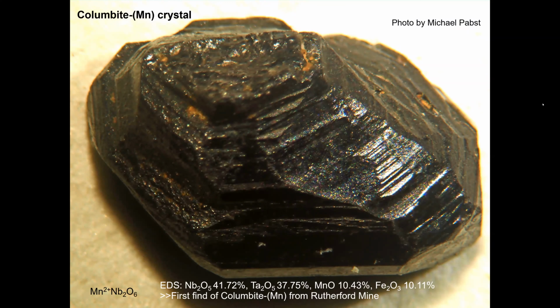This is interesting though. The analysis suggests that both tantalite-Mn and columbite-Mn were present in the pegmatite, and that due to the abundance of columbite-Mn, many of the specimens previously identified as being examples of mangano-tantalite were actually examples of this similar species. I would go out on a limb and say that probably two-thirds to three-quarters of specimens that right now we call mangano-tantalite were actually mangano-columbite. We won't know until we test every blasted one. Next slide.